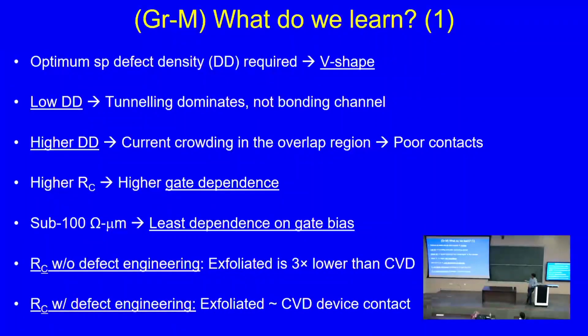So what we found there is an optimum defect density needed, which results in this V-shaped characteristic as a function of defect density. At a lower defect density, this is mostly tunneling contact. At higher defect density, it's mostly current crowding in the overlap region, which results in poor contact, so you need an optimum defect density. When you have very high contact resistance, there's also high dependence on the gate bias, and that's also something you don't want. You don't want your contact resistance to be a function of gate bias. But when we had this sub 100 ohm micrometer contact resistance, the gate bias dependence was the least.